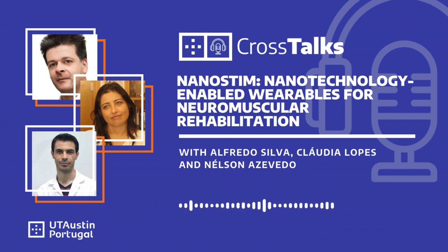It's really small. So by using this technique, under vacuum conditions, we eject titanium atoms from a target, through several elastic and inelastic physical collisions, and after sputtering, these atoms are specifically placed on the substrate, atom by atom, creating nucleation sites to grow. And at this nano level, it's possible to completely modify the properties of the sensor, because we are working with atoms.